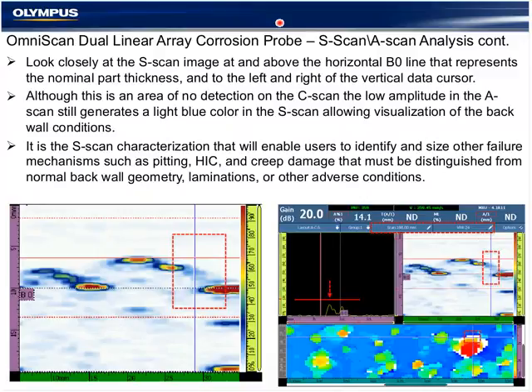A-scan and S-scan analysis is done using the blue data cursor on the C-scan. Even in areas where we have a white pixel, indicating no detection in the gate, we can still see by A-scan and S-scan analysis where the river bottom or back wall is in the corrosion. I can readjust the gate to try to acquire those data points, but that would normally contaminate the rest of the C-scan, so instead I use the A-scan and S-scan to make notes and understand what's happening.